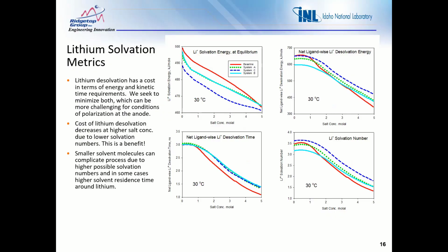Next slide. So there's different metrics of solvation that are provided by the model. I will just give a brief overview of these. First of all, at the upper left panel, we have lithium solvation energy at equilibrium. So this would be like the solvated lithium that is just hanging out there in solution at an equilibrium state, generally driven by concentration and temperature. As we look at the x-axis and go up in salt concentration, that solvation energy tends to drop because there's fewer solvators per lithium as you increase the salt concentration. So we have 4 different electrolytes shown here, ranging from a baseline, which is a carbonate-based system, to others that are designed more for fast charge applications.